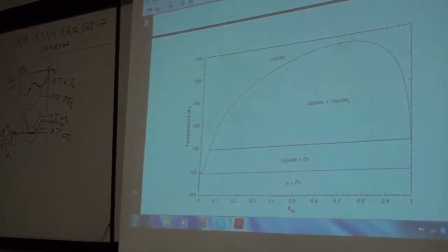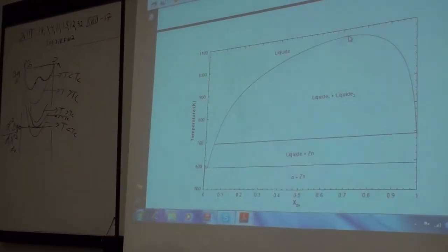Have any questions about this? So, of course, that just uses the critical point. We've used the measured critical temperature and composition in order to calculate A and B. This is probably something you wouldn't do in practice, the reason being that the critical temperature and pressure are really difficult to measure. Maybe even the critical temperature is hard to measure experimentally. The critical composition, this thing is really flat, so knowing where the critical composition is is pretty difficult. Nevertheless, you can see how it happens.